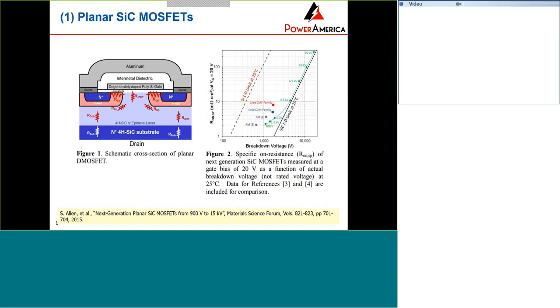If you take a look at the planar structure, the left figure shows a very simplified cross-section of the device, and the MOS channel is fabricated on the silicon face. The right figure shows all the devices that have been demonstrated on silicon carbide so far. You can see that silicon carbide devices have been developed from 900 volts up to 15 kV. That figure was published in 2015.